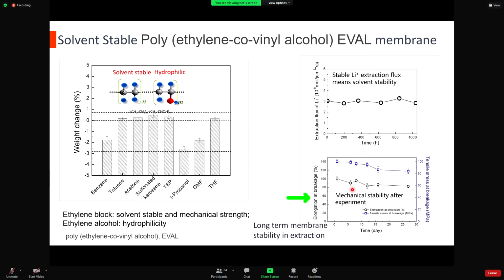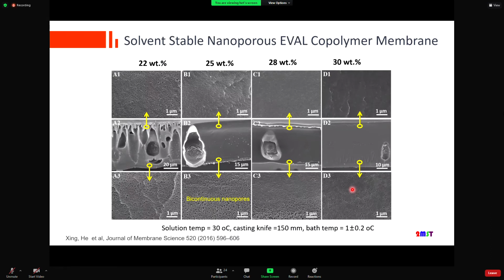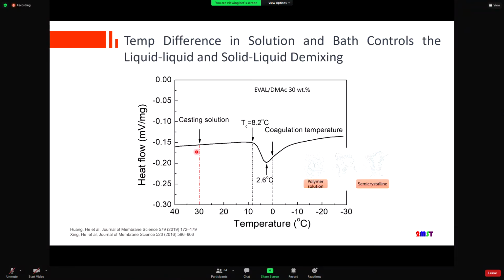But how to make this membrane? This is a scanning electron microscope image of the EVAL membrane we prepared in the lab. You see here, this is a nanoporous structure, bicontinuous, but there are micro voids in the polymer matrix. It reduces as we increase the polymer concentration. Controlling the morphology is critical for making such a membrane.